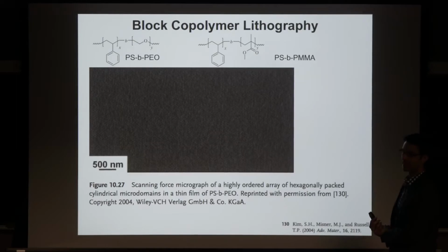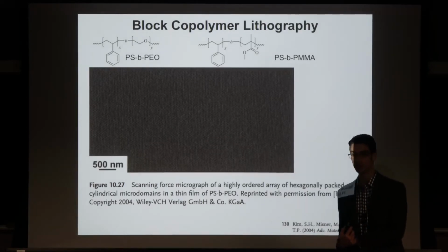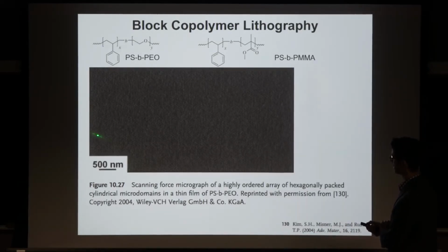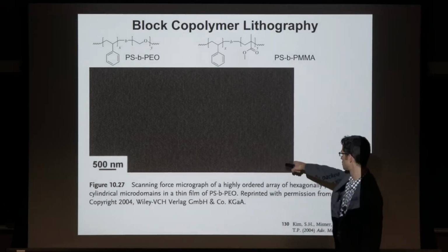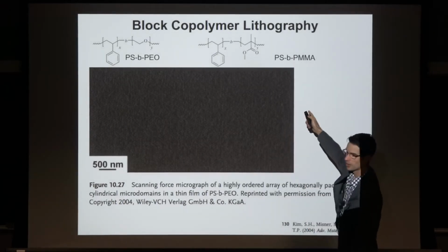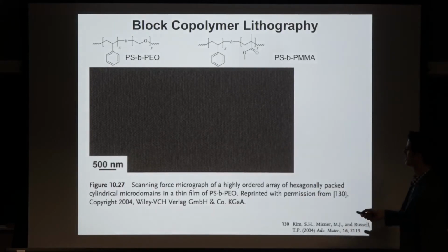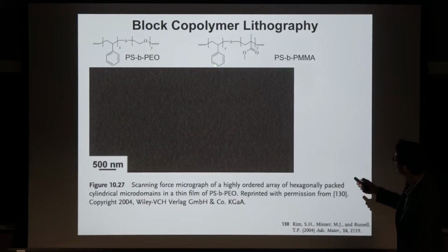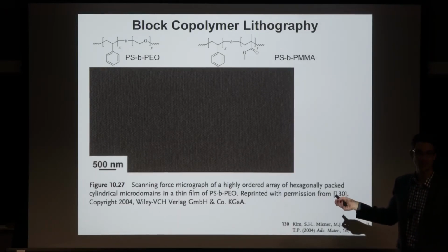So you want a low K dielectric material. We talked about this a little bit before. You can make air gaps, for example. If you have polystyrene block PMMA and you cast this film, this is a hexagonal microstructure, looking from the top down. So these little circular microdomains. What's amazing here is how well registered this structure is. This is several microns across, but you can draw a line. This dot here, straight line all the way across, straight line all the way down. And this is the structure that you get automatically.